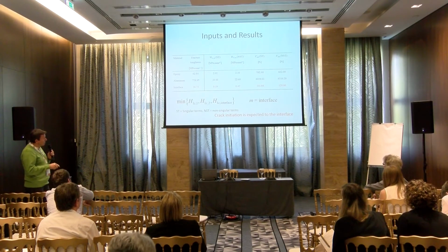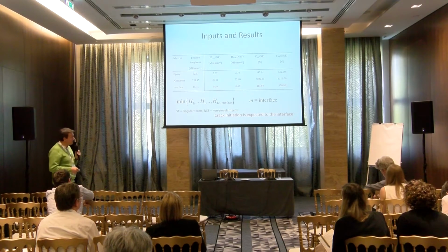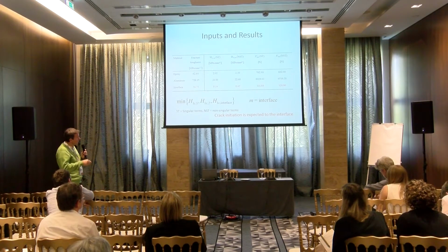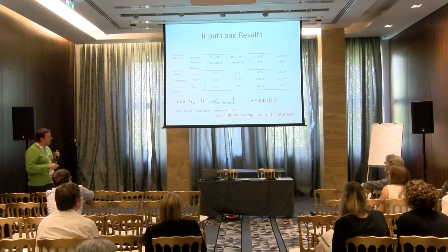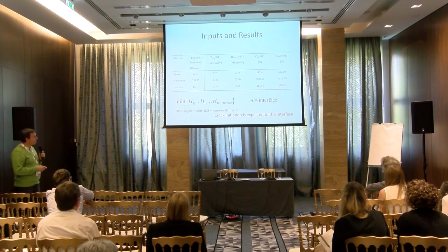So the lowest critical force is for the case of the interface, so we expect crack initiation into the interface, and you can see that using singular parameters or the multi-parameter criterion, the difference is about 8%.